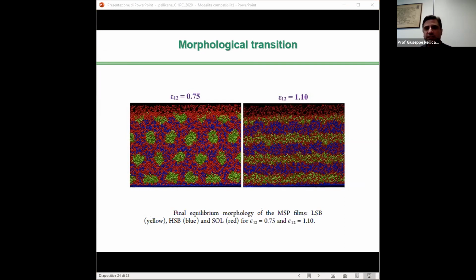In this slide, I'm showing two-dimensional snapshots of equilibrated morphology of MSP films, including solvent. And this is done for poor solvent on the left and good solvent conditions on the right. In the case of poor solvent, look at the panel on the left, it is clear that the solvent beads are abundant only within the regions occupied by HSB beads, since they prefer to interact with themselves and HSB beads at these energetic conditions.